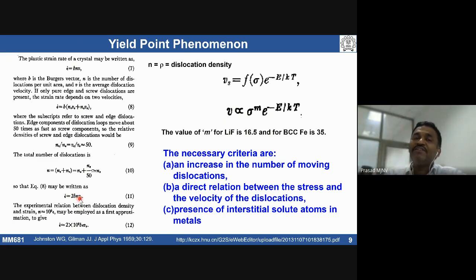After that, what happens? It has to maintain - the internal strain rate has to be maintained with the external strain rate. The balance has to happen. That means your velocity of dislocation should come down, in order to decrease the strain rate further.